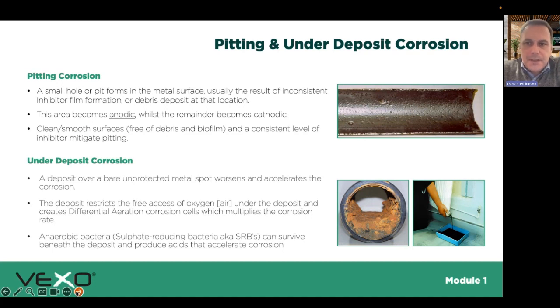Pitting and under deposit corrosion can be very similar in terms of how they look, but pitting corrosion is if you have a dirty pipe work, you're laying down inhibitor and you've got an inconsistent film. You have this demarcation where one side is anodic and the other is cathodic, because one side is being protected by inhibitor, the other side is not. And unfortunately, that's where we start seeing localized pitting corrosion on the surface.